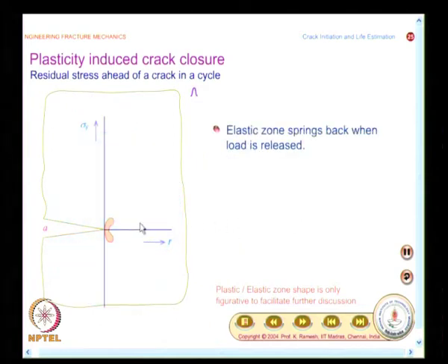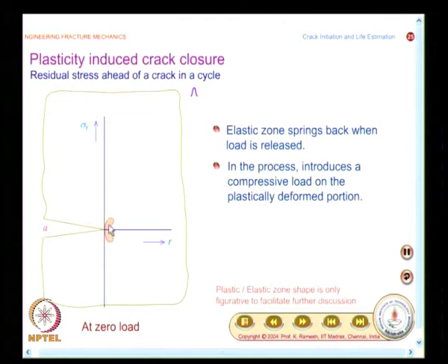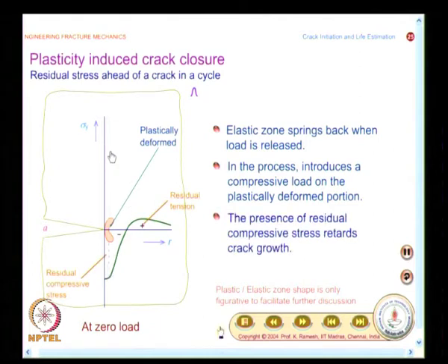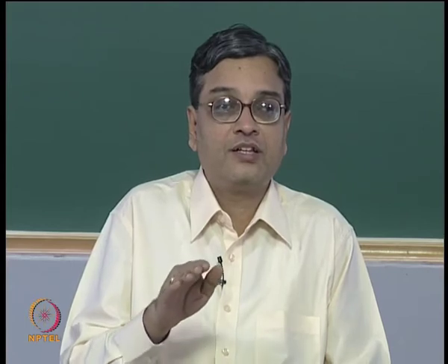So, what you find here is the elastic zone has recovered and the plastic zone has been compressed, and in the process it is pushed to the negative part of the axis. So, what you have is, instead of positive sigma ys to start with, it has a residual compressive stress in this zone followed by residual tension. So, what you will have to realize is, when there is a loading and unloading, this results in formation of residual compressive stress and tension.